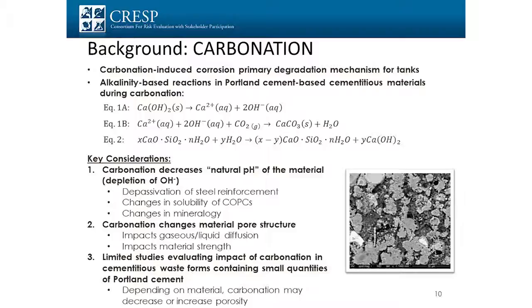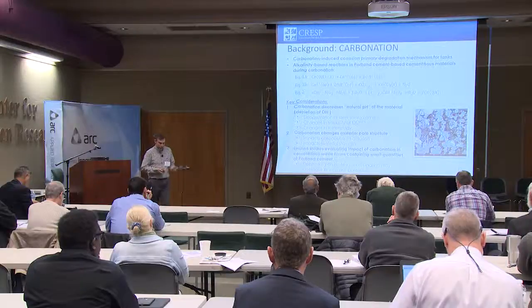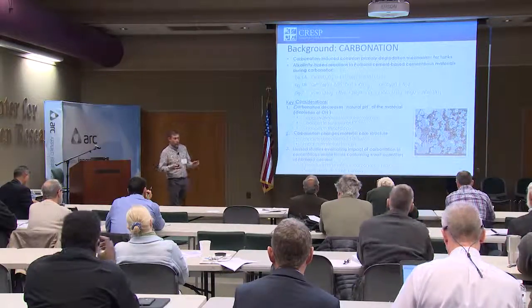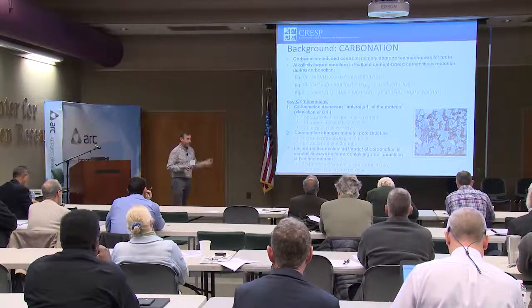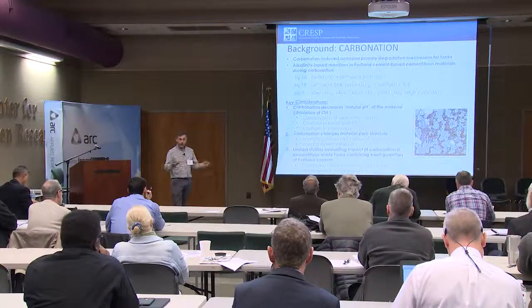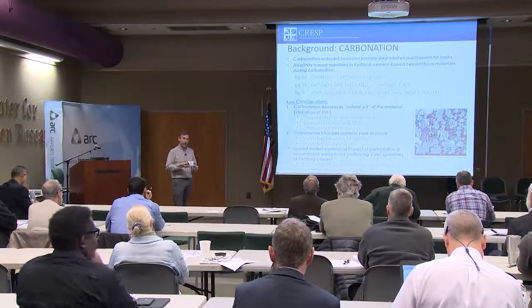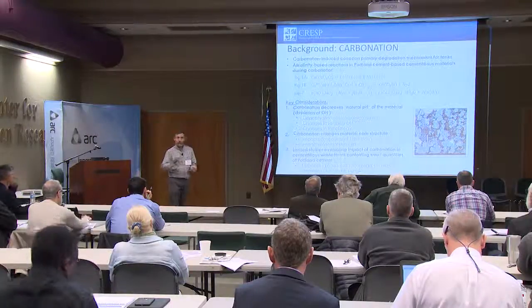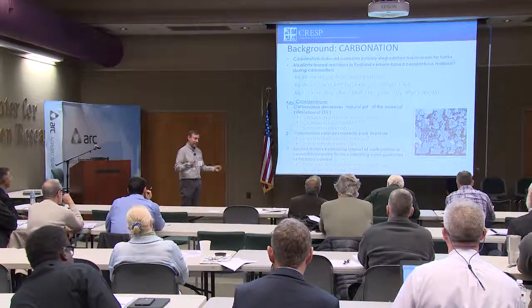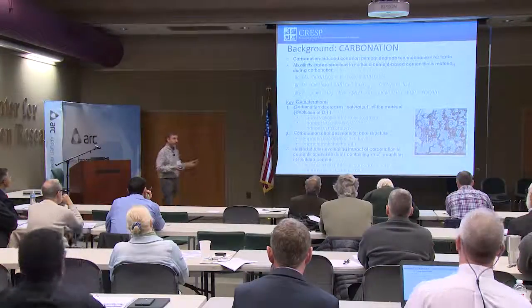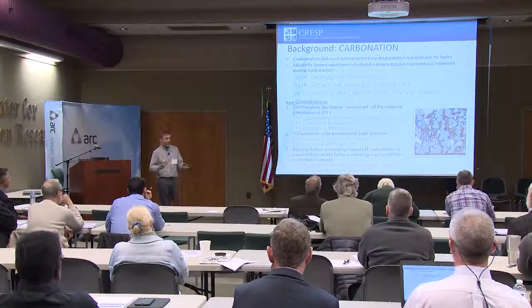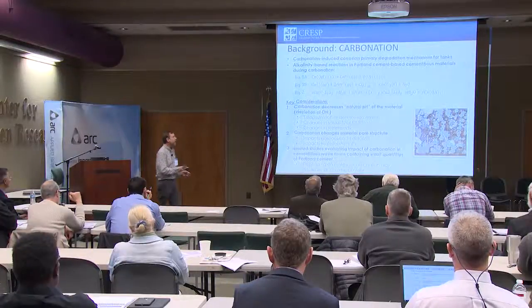And then there have been just limited studies on the impact of carbonation in these waste forms for small amounts of Portland cement, which is where people go. But these changes depend on the material. So if you have something that is, say, Portlandite primarily, and you start carbonating it, you'll get a refinement of the pore structure. But if you have something like a geopolymer or something with ettringite in it, as you carbonate, you actually lead to expanding the pore structure. So it does depend on the material. It doesn't always close the pore structure. Sometimes it can open it up. So you have to be careful what kind of material you're looking at.